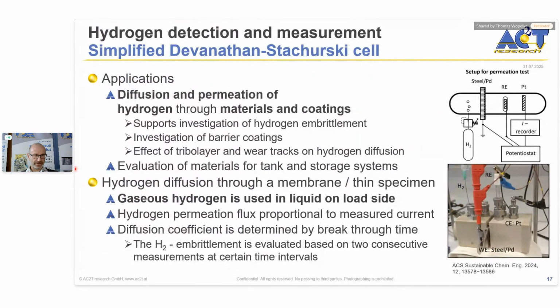So you can see on the right side, on the top, a chamber which is filled with electrolyte, and the two parts of the chamber, the left side and the right side, are separated by a membrane, and this is the material you want to investigate. In this case, it is the steel membrane, which is coated with palladium on the surface. On the left side, you flood the chamber with gaseous hydrogen, and the hydrogen is dissolved in the electrolyte and then diffusing through the steel membrane towards the right side, and the atomic hydrogen is oxidized by the palladium coating, and it creates protons.